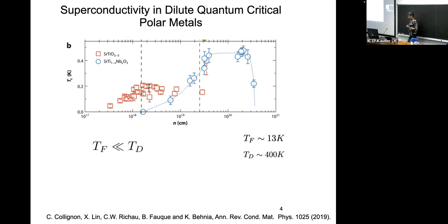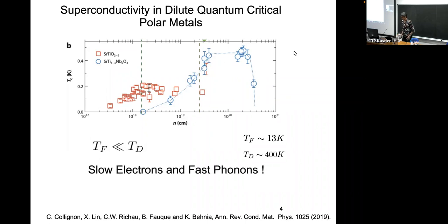Okay. TF, for example, for these densities is about 13. TD, the Debye temperature, is 400. That means that TF is much, much less than TD, and we have slow electrons and fast phonons. Now remember that for BCS, we want fast electrons and slow phonons. Remember, normally we have TD less than TF, but here we have the opposite way around. Okay, so we cannot use the conventional BCS theory in this.